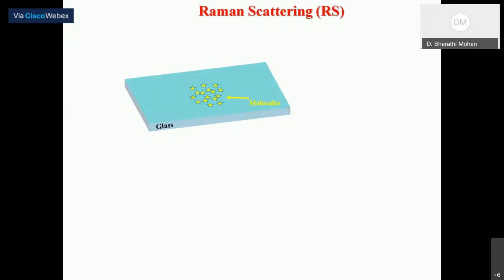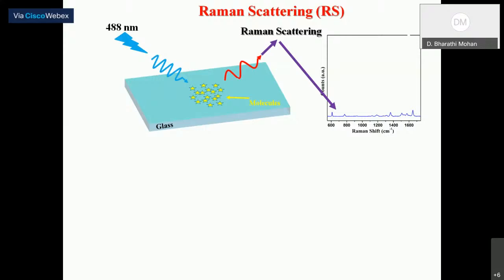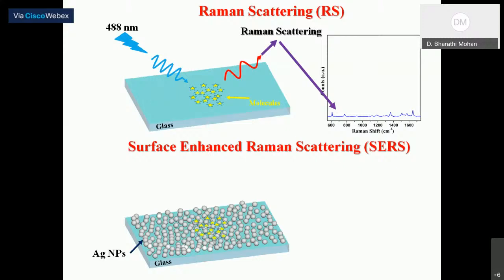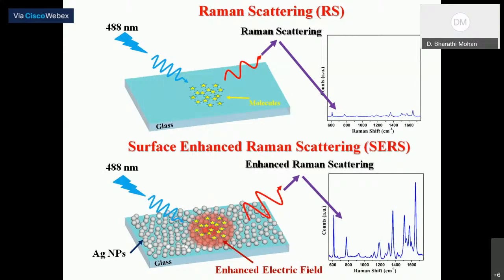What is the difference between normal Raman scattering and surface enhanced Raman scattering? You take a glass substrate and deposit a probe molecule, and you want to check the chemical structure of the probe molecule using a Raman spectrometer. You excite with 488 nanometers, and it shows a Raman spectrum with very low intensity. Whereas if you take a glass substrate, deposit silver nanoparticles, and then drop cast the probe molecule, the Raman study shows enhanced Raman scattering. In this way, just by depositing a probe molecule on top of silver metal nanoparticles, one can enhance the Raman scattering of the probe molecules. The enhancement factor can be calculated using this equation.